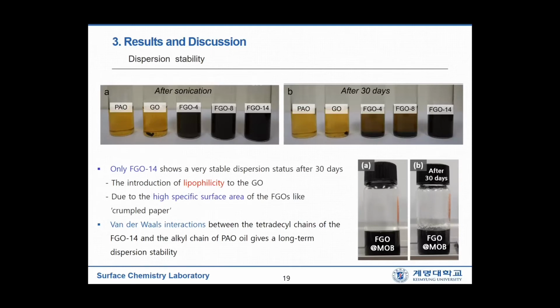This is the test result for dispersion stability. After sonication of the mixed systems for an hour, FGO samples are all dispersed, even though the GO was not dispersed due to its hydrophilic property. But after 30 days of storage, only FGO14 showed very stable dispersion stability. This is due to the introduction of lipophilicity to graphene oxide.